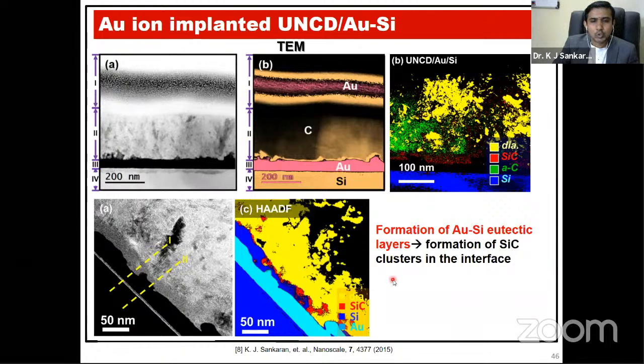So the formation of the gold-silicon eutectic layers that form the silicon carbide clusters in the interface helps the electron transport, and the nanographitic phases in the interface also make a very good transport mechanism, which helps better field electron emission properties.